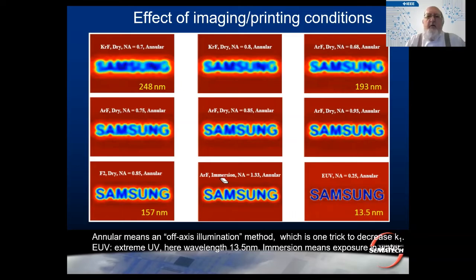And taking 193 and doing an immersion with that, if you remember, that gives you like a 50% increase in the numerical aperture. So there you see a spectacular numerical aperture and a really good resolution. But there we are, bad numerical aperture, but 13.5 nanometers gives you a very high resolution. And that, my friends, is what's enabling 5, 7, and 3 nanometer type of devices.